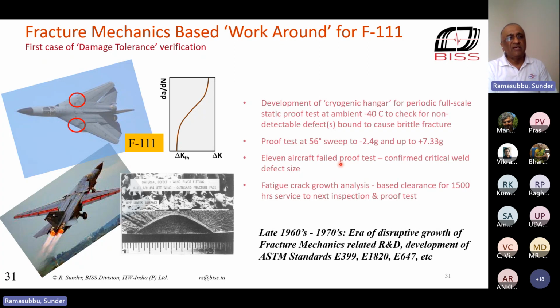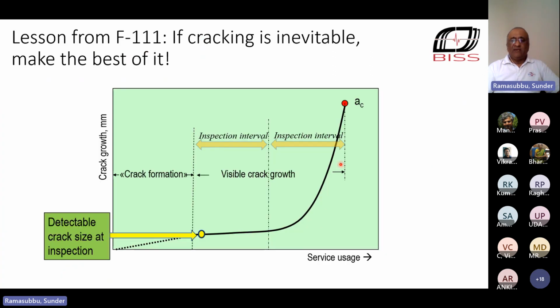It's from the aerospace attitude of aircraft that all these things have now percolated into various industries as well. And the idea is very simple, that if cracking is inevitable, we have to make the best of it. And how do we make the best of it? We count on the crack as an indicator of condition. And if there is a crack of detectable size, we then look at how long it will take to grow and divide that by a factor of 2 and assign that as the inspection interval.